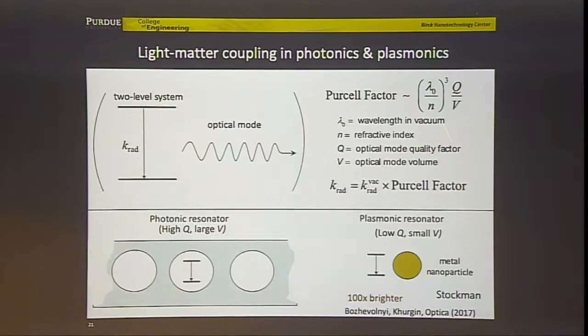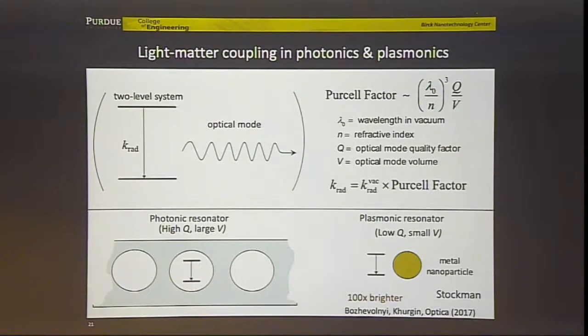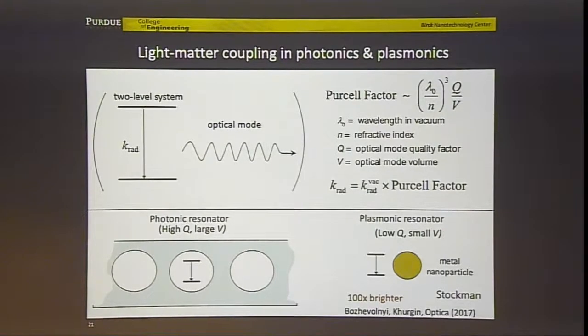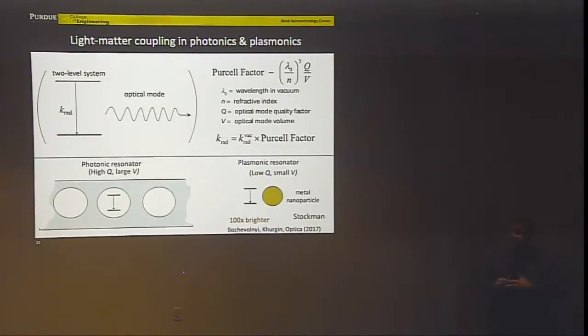But you need to get the same high ratio. How to do it? The volume. What is unique about plasmonics is that it confines electromagnetic energy into exceptionally small areas, like 5 nanometers. 5 nanometers is 100 times smaller than the wavelengths in the visible, 500 nanometers. You should take it to the power of 3 because it's volume. It's 1,000,000 times enhancement just because of the confinement. Plus Q could be 100, so it's 10 to the 8. It's the same strong Purcell enhancement, but Q is small, and therefore the system is fast and broadband. Now we're talking. Now we could take advantage by doing the processes faster than decoherence.